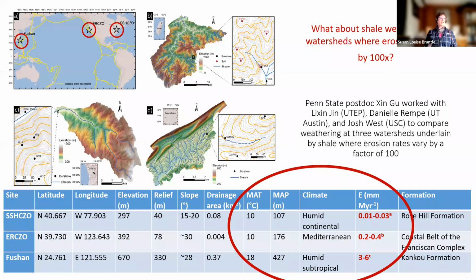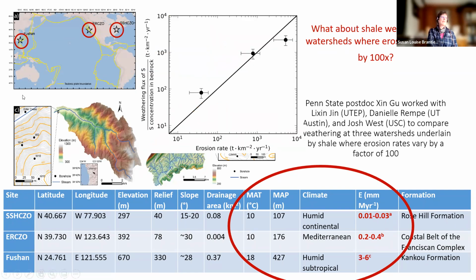And so we asked the question, first of all, how much sulfate is being released in these watersheds? Because that tells you the weathering rate of the pyrite most directly. And so when you plot the weathering flux of sulfur out of each of these 3 systems versus the erosion rate, and we had to do the weathering flux divided by how much sulfur there was in the bedrock, because there were slightly different pyrite contents, you do see that the sulfate release rate increases with the erosion rate. So it does seem like it is being paced by the erosion rate, which makes sense based on some of those models that I showed you earlier with the reactive transport models.